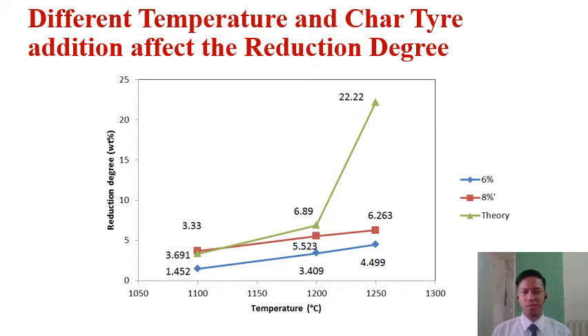Thus, when compared to the theoretical level, or the green line, this shows that the hematite has been partially reduced to magnetite since it did not reach the supposed theoretical level. Then in the second reduction reaction, the magnetite has been partially reduced to wustite, and at 1250 degrees Celsius, the wustite has been slightly reduced to iron, while having most of the iron phase in wustite and magnetite.